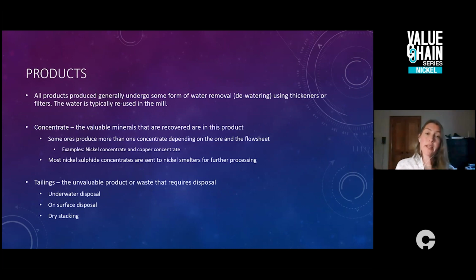And then that concentrate, for most nickel sulfide mills, is fed to a nickel smelter. That is changing as we move forward, if we look at where the nickel market's heading. I think we're going to see more and more nickel concentrates going either to hydro processing for batteries potentially, or into, say, roasting and going directly into ferronickel for stainless steel. There's lots of opportunities there, but traditionally, the nickel concentrate that was produced from a mill would then go to a smelter. And that's really no different than, say, copper or zinc.